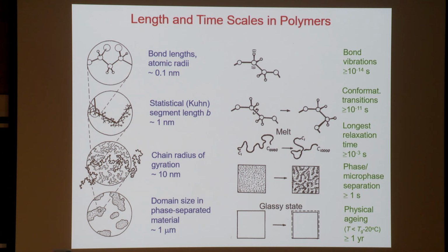Longer and longer sequences of chains take more time to conformationally isomerize until we come to the longest relaxation time in a melt, that is the time required for a chain to diffuse by a length commensurate with its size and forget its previous conformation. And for even modest molar masses, this can be longer than milliseconds.